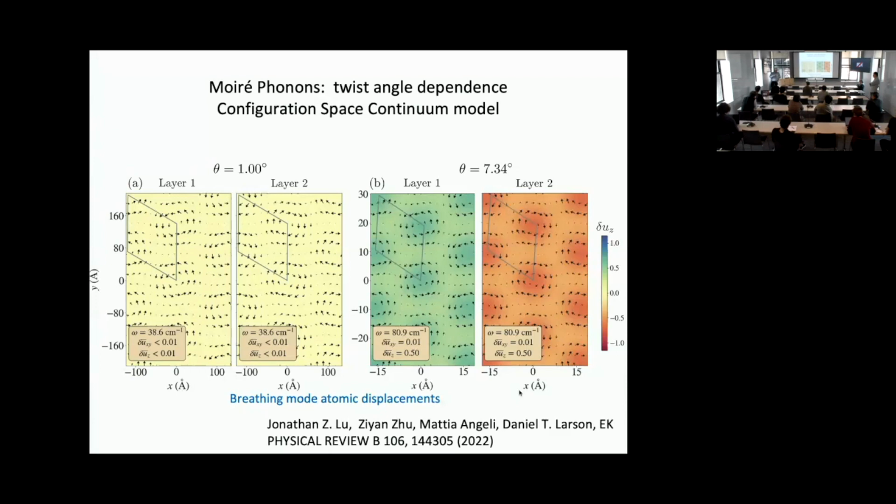The hBN has a different lattice constant from graphene, and the alignment is not usually perfect. So essentially, this leads to an average potential from hBN on the graphene layers, and it's this average potential that washes out and doesn't strongly affect these states. That's the sort of picture that I have in my mind. Unless you take care to very carefully arrange the two layers so that an overall pattern emerges and affects these states, I don't think it's a big effect.